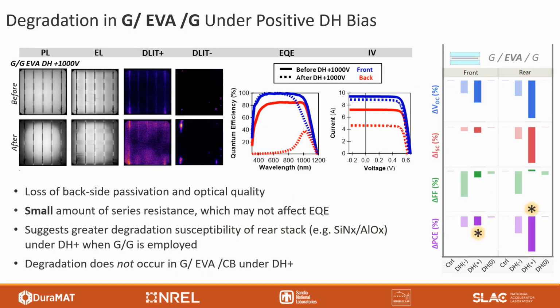The other interesting degradation process that I'll note is the positive bias damp heat for the glass-glass EVA sample. In this case, we saw minimal resistive effects, and the degradation was mostly dominated by loss of the backside passivation and optical quality, which is shown by the severe loss in VOC and ISC. From the images, we see an overall loss of luminescence signal and increase in the heat dissipation, but the degradation is most severe as a halo around the module edges.